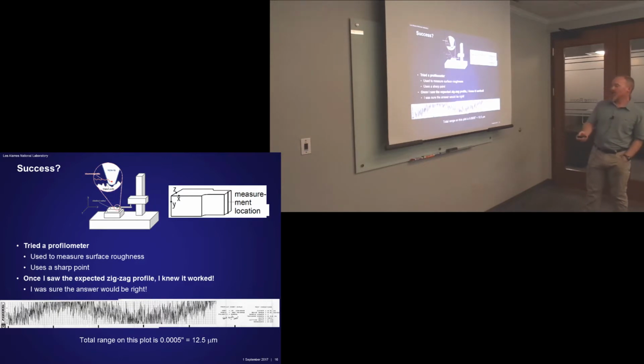And I was thrilled, though. If you look at this, you can see all the noise from the surface roughness, but you see the zigzag, right? Up, down, up, which looks like that bent beam stress profile. I was absolutely ecstatic that this is going to work. I was sure the answer was going to be right. And by the way, the range on this is half of a thousandth, so about 12 microns. So it's a pretty small signal, but it seems to be there. I was absolutely thrilled.